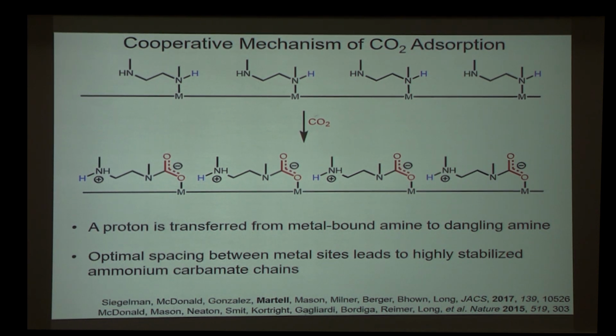A lot of work by current and former members of the Long group has elucidated the mechanism of cooperative CO2 capture, and I'm depicting that here. What I'm showing at the top is the amine-appended material without any CO2 present. So here are the metal-amine bonds. And upon addition of CO2, it inserts into the metal-amine bond, creating a carbamate with its oxygen coordinated to the metal site. And what was a dangling amine has been converted to an ammonium, and the spacing between metal sites is perfect to allow for highly stabilizing ion pairing in between the ammoniums and the carbamates. So we have chains of ammonium carbamate running along the long axis of the material.